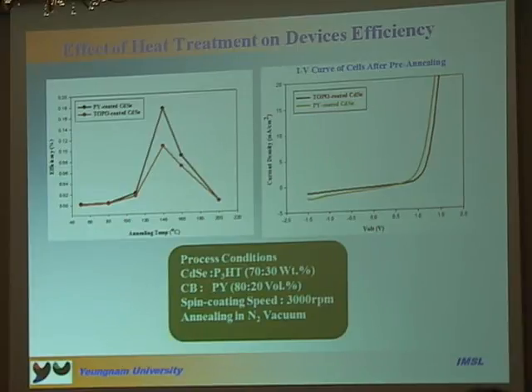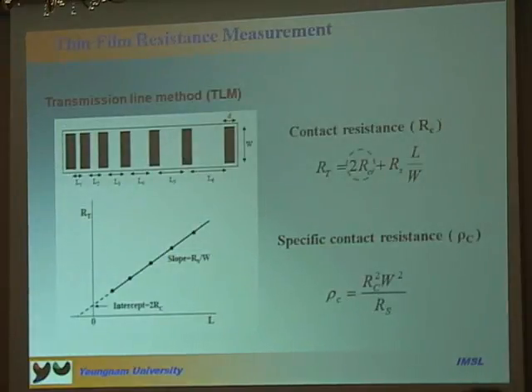This is the case of pyridine coated CdSe and TOPO-coated CdSe. And on the left side, we can see the solar cell after pre-annealing and the process. This one is the process condition. Besides material related problems, interface problems, and surface morphology problems, we also try to know the property of the material at the interface of the active layer. So if we reduce the contact resistance, that's why we use the transmission line method to measure the specific contact resistance of the composite film.